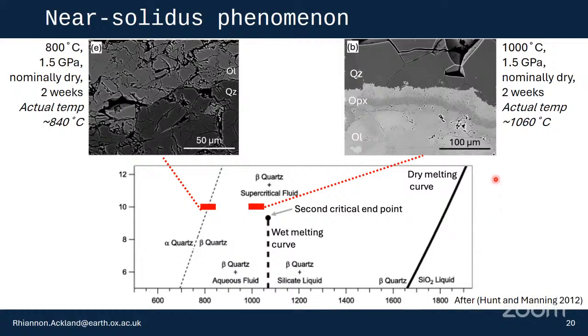So whilst the region with the thermocouple is at 1,000 degrees, my experimental runs were generally at higher temperatures, around 1060, and so in the vicinity of the wet melting point of quartz. The fact that at 800 degrees, where we're far away from the wet melting point of quartz, we see no reaction suggests that a small degree of melting is required for these reactions to take place, whether that be melting of the quartz completely, or what I think is more likely, a small amount of pre-melting behavior, where you only get thin melt films forming along crystal boundaries.